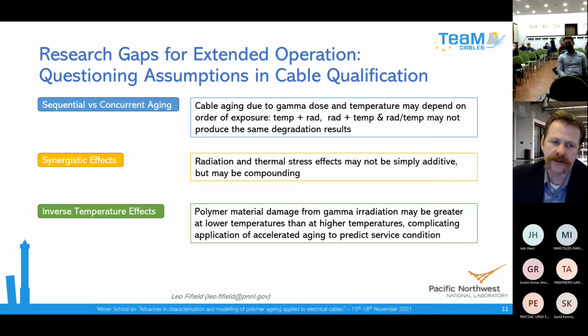All this relates to how long we can expect those initially qualified cables to last. So for instance, if we had some of these effects like DLO and we overestimated their performance in accelerated aging, the concern is that when we thought they were going to last for hundreds of years, it turns out that they only last for 50 years, and then maybe they need to be replaced before we relicense the plant to operate to 60 or 80 years.